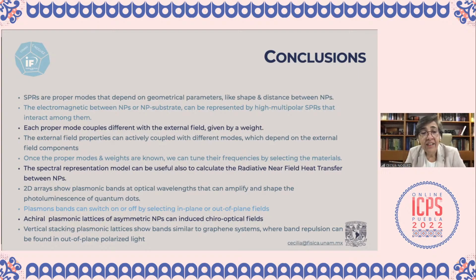Okay, and the external field properties can actually couple with different modes. That depends on the external field components. That means if you are looking at polarization along one direction or the other, we can tune in some way the frequencies, and we can select the materials, and we can select the arrays, and we can do a lot of things. And this can control the radiative heat transfer. It can control the photoluminescence of quantum dots, and also the chiroptical effects or chiroptical fields in order to test chiral molecules and so on.